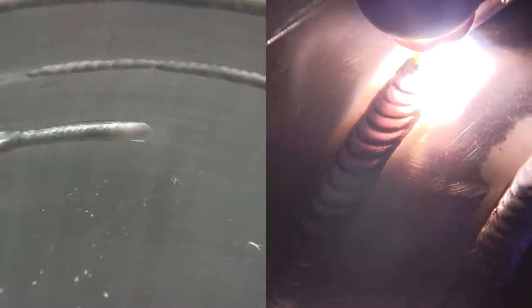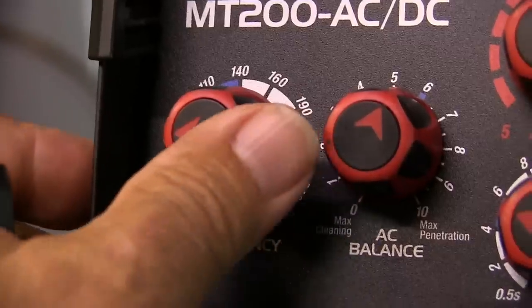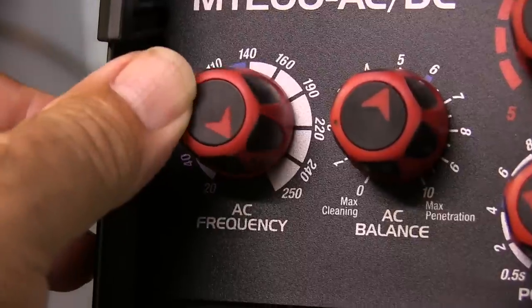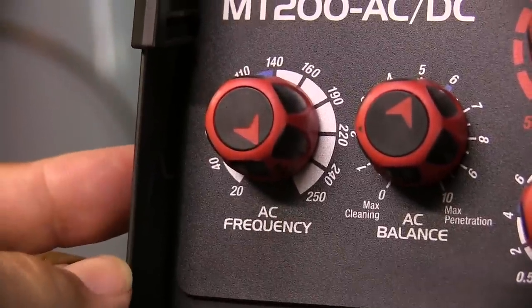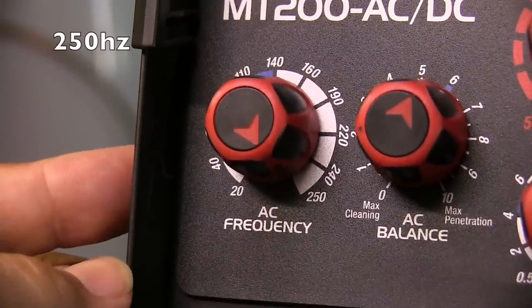I put a camera on the backside so that you could see that molten aluminum just going along real time as I weld along the top of this piece. Penetrating nice and smoothly, evenly, like you would want it to if this was a butt joint. But now, if I set that frequency all the way from 50, I'm going all the way up to 250 just to swing the pendulum really far one way, and you can see the difference.